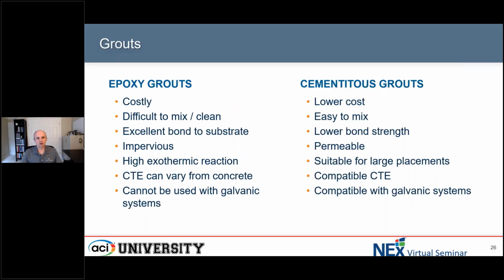So just a couple of notes on the grouts. The grouts that are used, again, are generally either an epoxy grout or a cementitious grout. Epoxy grouts are, at least in my opinion, tend to be a little bit more durable because they do bond much better to the concrete substrate, and because they are impervious, they don't have a lot of issues with water and oxygen infiltration. So these epoxy grouts tend to be more durable, but they are certainly a lot more costly